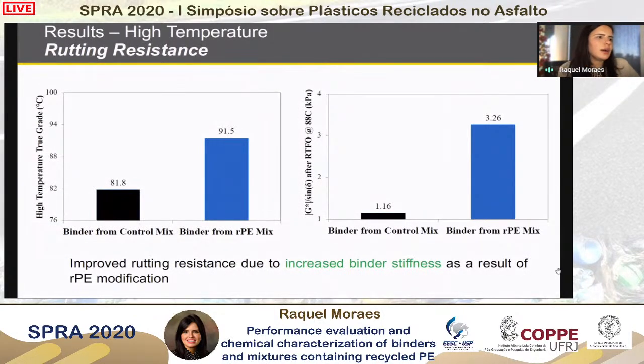So we have the high temperature continuous grade on the left side, and the G*/sin delta at 88C for both binders extracted from the control mix and the binder extracted from the mix containing the recycled plastic. And we can see by the results presented over here that we see improved resistance to rutting, because we see an increase in the binder stiffness as a result of our RPE modification, even though the recycled plastic was incorporated to the aggregate via wet process. We are seeing here change on the properties of the binder itself.